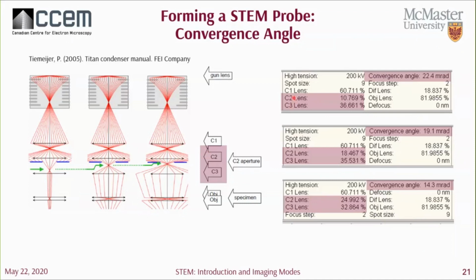As shown here, increasing the strength of the C2 lens will decrease your convergence angle. And here we have the same idea in which changing the C2 lens, there's also a little change in the strength of the C3 lens. It was adjusted accordingly so that the crossover of the final probe on your specimen, the position, remains fixed. It's also worth noting that at this step, in changing the C2 lens, the strength of the C1 lens didn't change, so the brightness didn't change. That only changes when we choose a spot size.